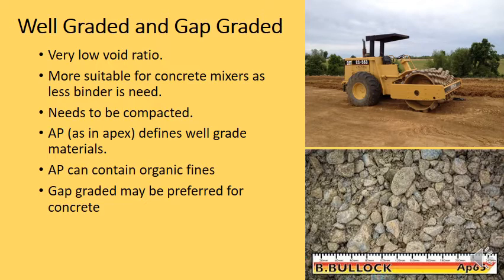Now, one of the other things with well-graded and gap-graded aggregate is that it can actually bulk up. So you can have big voids inside. If you just pour it out onto the ground, you can then stand on it and press it down because big voids may be inside that aggregate unless it's been compressed, meaning that you haven't pushed the smaller aggregate particles in between the larger aggregate particles.